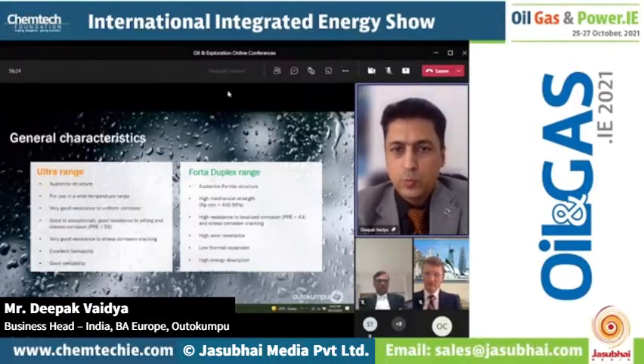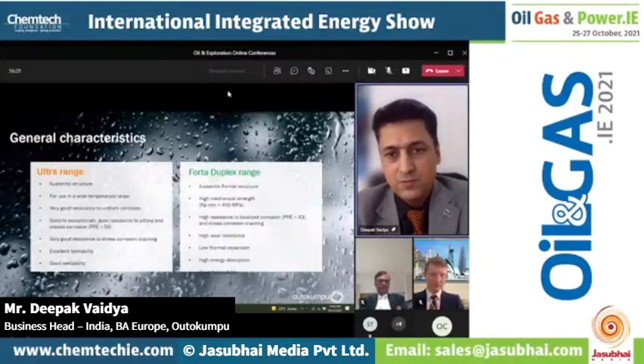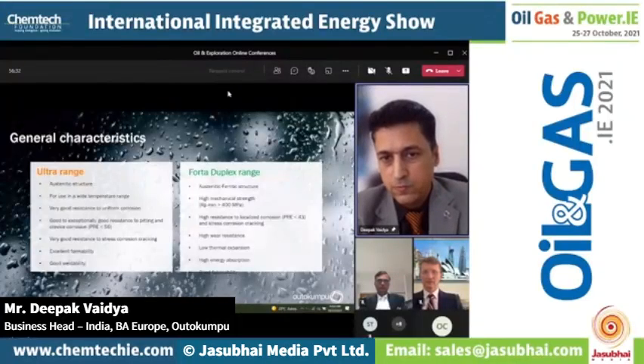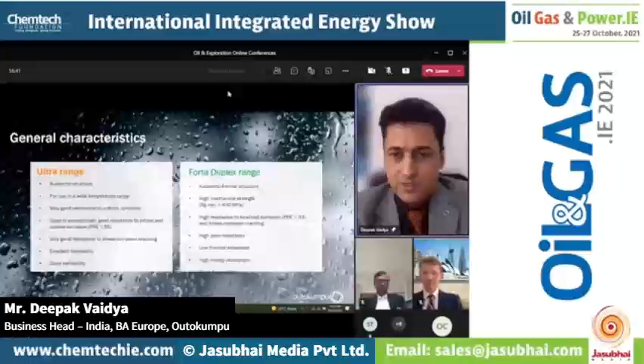When you talk about duplex stainless steel with austenite-ferrite structures, strength is more than 400 megapascal, which you can use to reduce the thickness. As we go further, you will understand how it is done. It has very high resistance to localized corrosion, up to 43 PREN, high wear resistance, low thermal expansion, high energy absorption, and good fabricability. These are the parameters.